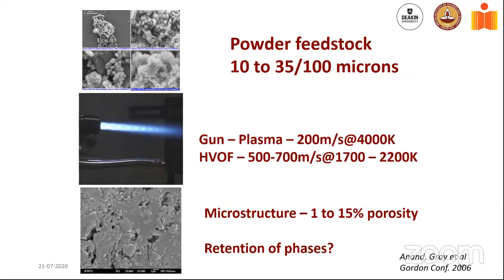But the trick is two things. One is that I want to have a coating which is dense. So I don't want a porous coating which has poor integrity, because the pores essentially are crack formers. The pores would then come together and form a crack, and the crack would propagate. And irrespective of how good your material was, because it is deposited in a manner of poor integrity, the whole thing would come apart.